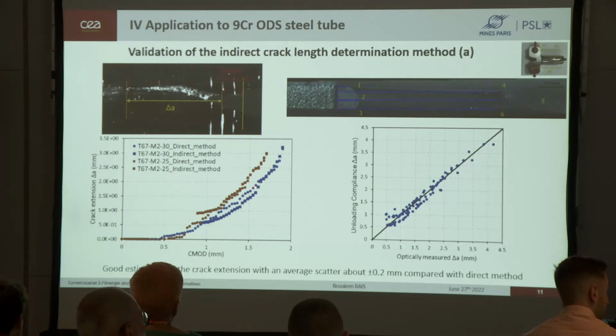So as we can see on this curve, which is the crack extension as a function of the CMOD, the indirectly estimated crack extensions and the directly measured crack extensions follow the same evolution. And if we plot the unloading compliance estimated crack extensions as a function of the optically measured ones, we can see that the points are around this line, which is the one slope line. So we have a good estimation of our crack extension with an average scatter of about 0.2 millimeter.